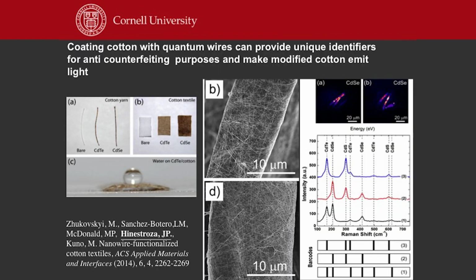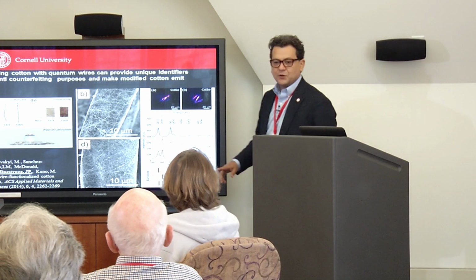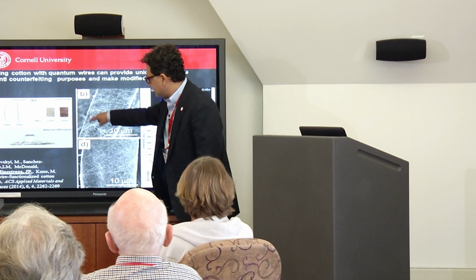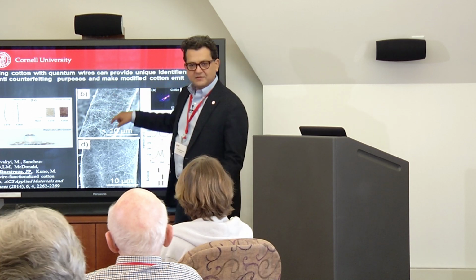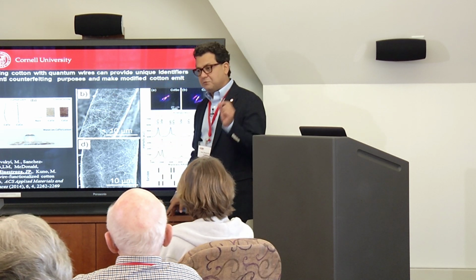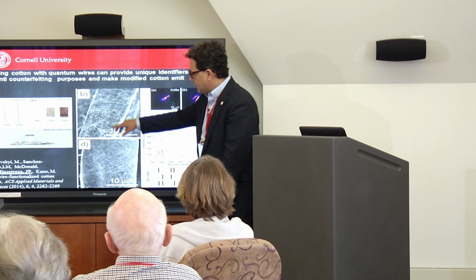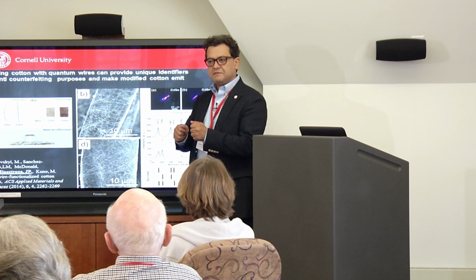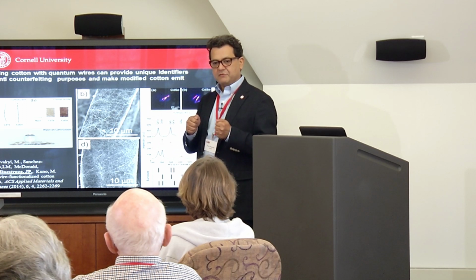And now, one of the last things we are doing is, instead of placing particles, we are actually making wires. Because with particles, when you have abrasion, they may detach. But now we grow these wires like an anaconda, so it goes around and around the fiber. They're very, very small, a few nanometers. But when they go around and around, they give mechanical stability to the fiber.